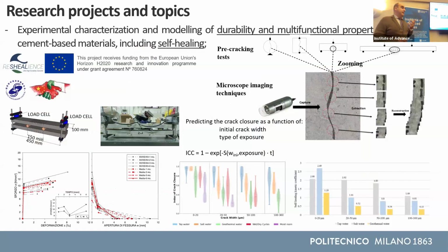How can you predict the maintenance? This was the other issue. Most of all, because you use UHPC almost in most cases without ordinary reinforcement. So if you think of the model for corrosion, you do not have a bar which corrodes there, so you cannot apply this model. So we investigated the long-term performance with experiments and modeling. I will not go into the details. We used also a little bit of AI to reshuffle things because we had a good database of about, I think, more than 750 cracks that we could scan. So it was a good database to train our own model. The paper was just published yesterday. Our student was very, very happy about that.